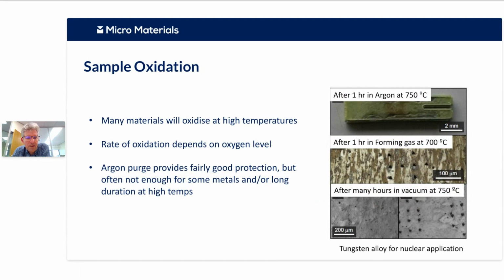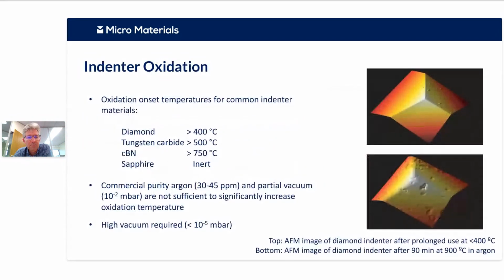With forming gas, you're getting still some degradation, relatively localized oxidation, and the vacuum is giving you a perfect surface, exactly the same after many hours or even days in vacuum. So there's no degradation. There's exactly the same native oxide thickness as is there at room temperature. And that's down to this very good vacuum level that we can offer in the system.